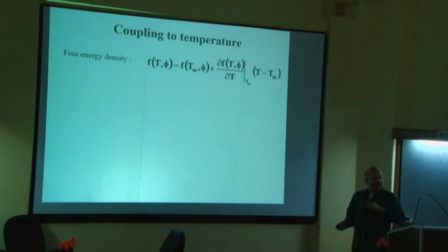As I said, what I have just given you, the interfacial part, would be the free energy of the system at the melting point. So now we have to extend this free energy to other temperatures than the melting temperature. And since we are generally interested in the vicinity of the melting point, I can just write a Taylor expansion. I can say the free energy is equal to the one at the melting point, which will be the interfacial part, plus this derivative times T minus Tm.